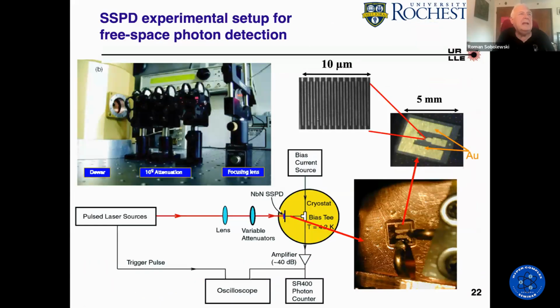And the experimental setup is extremely simple. The device is inside a dewar at 4.2 Kelvin. And you can take any source of light. You can have a flashlight. We happen to have femtosecond lasers in my laboratory, so we would use femtosecond lasers. You have a bank of neutral density filters, and you could lower the intensity so that on average you have less than 1 photon per pulse, and then we could easily count all those photons.